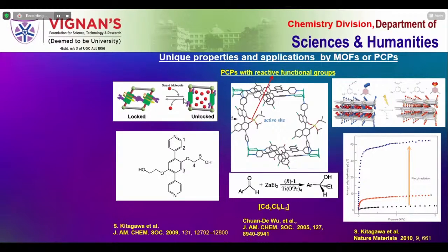Because conditions are also very important when applying the hydrothermal reactions. In a simple hydrothermal reaction, we take the ligand and dissolve it in a solvent, and take the metal salts and mix them, maybe in a 1:1 ratio, or we may have to vary it by trial and error, because similar to organic chemistry, we cannot fix the quantities equally. Sometimes if you use the exact ratio, it may not work.